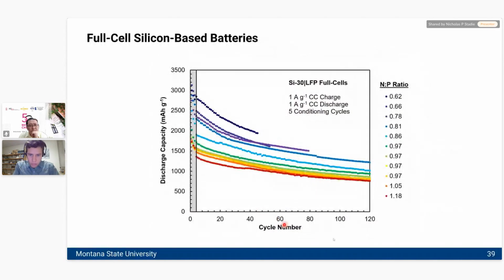So I'm just going to show you some performance and some different tests we ran afterwards. Most of this is more on the applied side, trying to figure out how to make these electrodes even higher performance. First of all, we put these electrodes in the presence of a full cell, so now we're cycling them against lithium iron phosphate once again, and changing the relative ratios of the anode to the cathode. If you change the amount of potential cathode lithiation supply in the material, that changes P, and if you change the relative amount of anode, that changes the amount of N. That ratio will give you some expected balance of the cell.